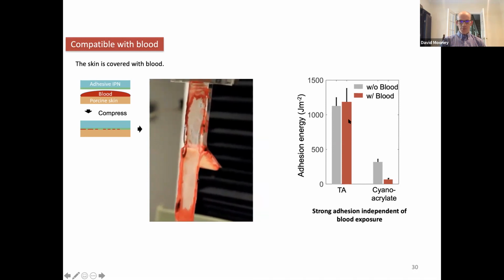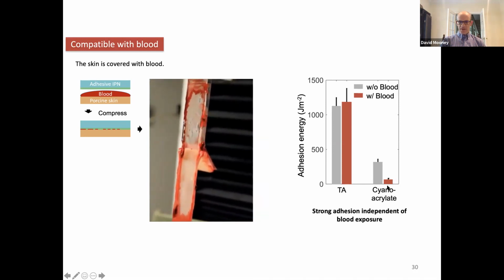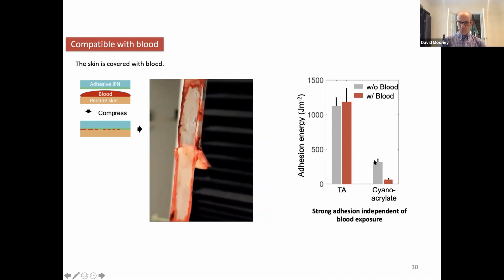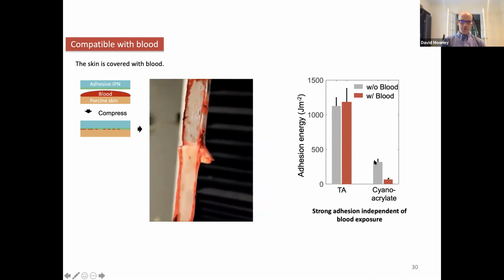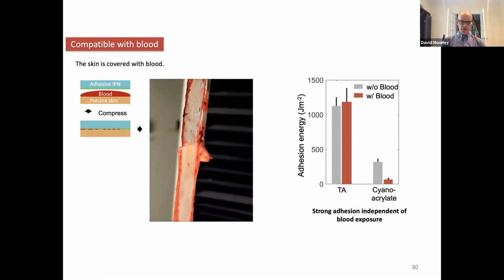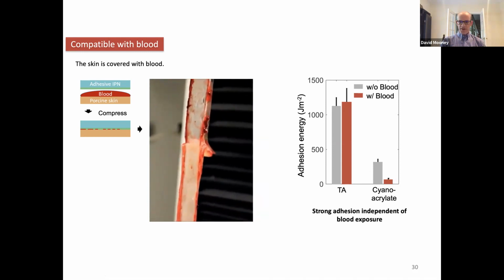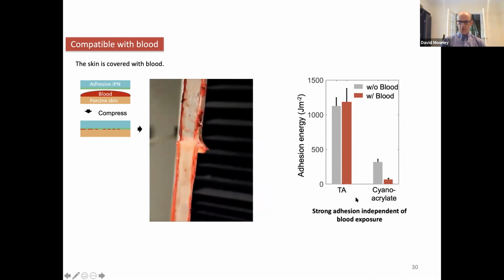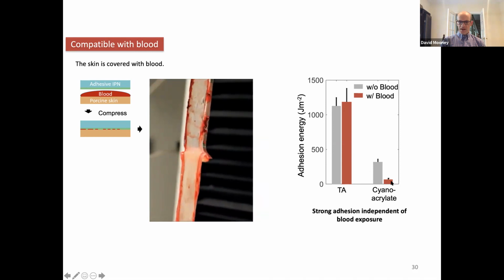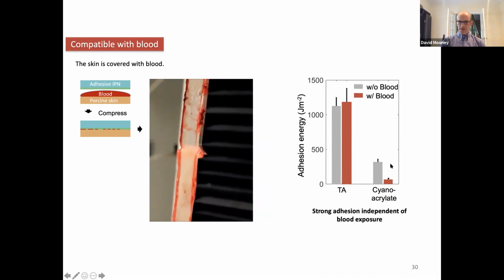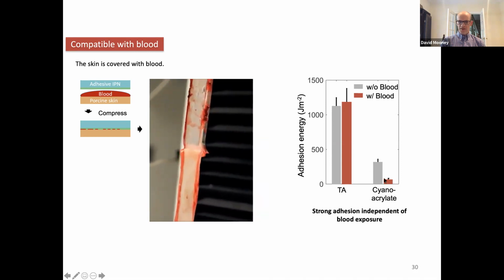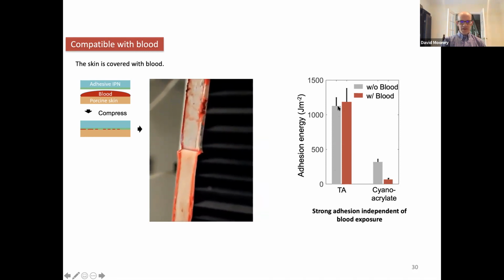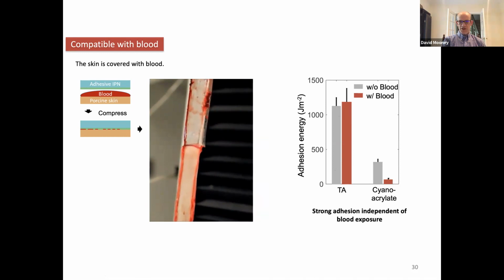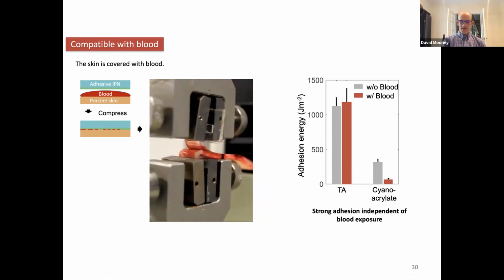This dramatically outperforms the industry standard cyanoacrylate or superglues by several fold. And a really key feature is that cyanoacrylate, as many of you are aware, if it's exposed to aqueous fluids, it actually does not set appropriately, so the adhesion energy dramatically diminishes in the presence of blood. But the tough adhesive system, its adhesivity actually is unchanged by the presence of blood,